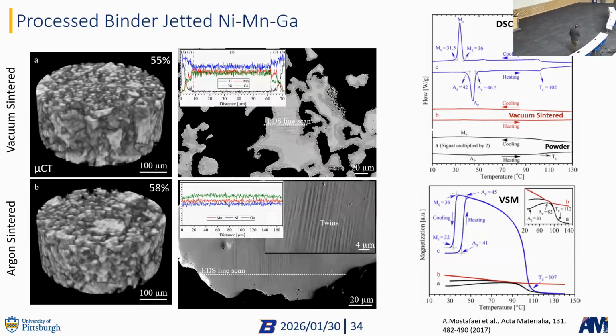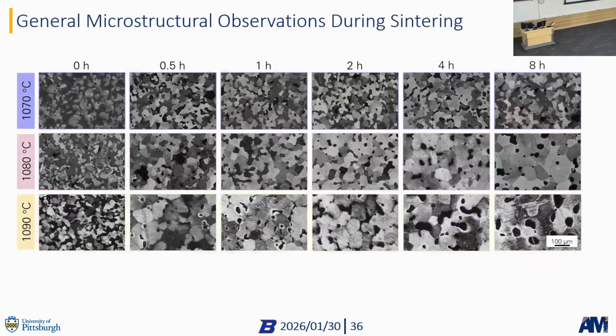So here on the right side, you see differential scanning calorimetry graphs, which show you phase transformations, for example. In vacuum sintered, you don't see any of them, right? This here is what you should normally see, like martensite phase transformations. Here you see magnetic functionality, and that's also completely gone for our vacuum sintered material. But if we backfill with argon, our structure looks actually pretty good. We have twins, which indicate martensites. We also see phase transformations and really good magnetic behavior. So atmosphere plays a big role in these materials.